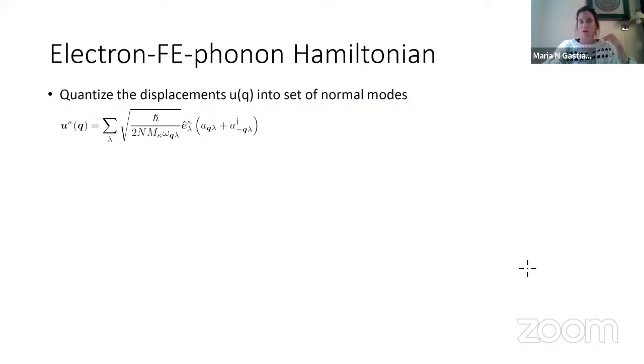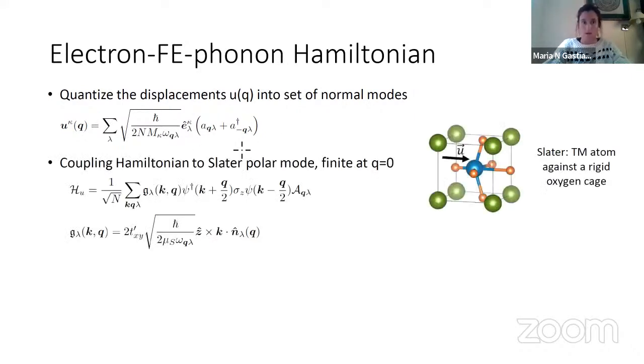So I was using classical displacements until now. As I said, my goal is to try to get an electron-phonon Hamiltonian, so that then I can use it for superconductivity. So now that I have my classical displacements, I quantize them into a set of normal modes, the textbook way of doing it. You decompose it into a set of orthonormal modes, and you write the previous expression in this formalism. And now what you get is an electron-phonon coupling where the bare coupling will be proportional to K. It will couple to a particular polarization of the modes.